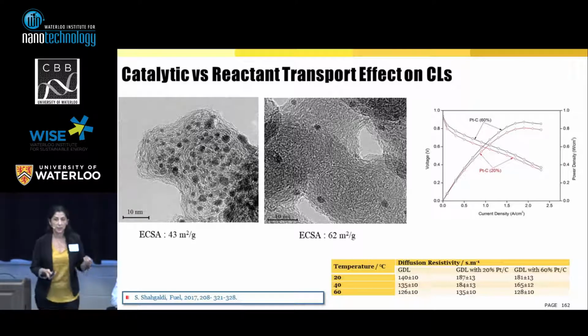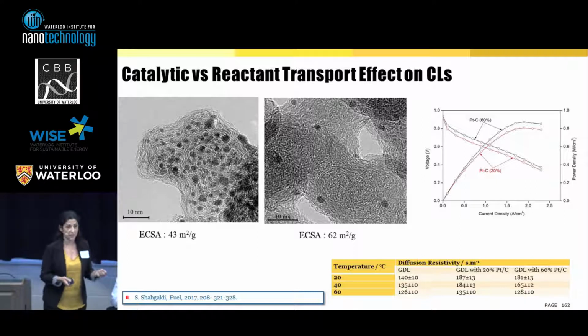Not only the microporous layer, but also we did a lot of work on commercial catalysts, like platinum carbon. We have different kinds of platinum carbon with different ratios of platinum to carbon. If we go through the literature, we will find there is a lot of research on the half-cell result, like ex situ experimental result. So if we compare these two catalysts together, we will find the active surface area of the catalyst, for example, is comparing between 43 to 62.